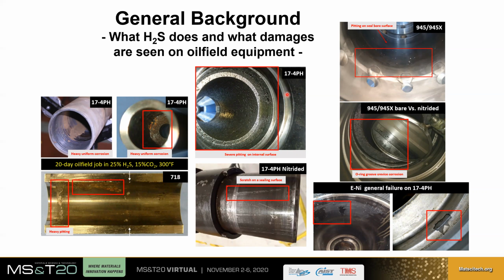For a different job, you can see here essentially heavy pitting on the internal diameter of some pressure housing. On the lower picture, you see a different type of damage, which is not really H2S specific, but nonetheless is very common in equipment. What we see here is a scratch. There was a sealing surface, there is a scratch. That means this surface is not going to have the same sealing ability, and it's a damage. Because this type of damage is quite common, this is one reason why we are forced to look at tribological solutions, namely hard coatings and hard surface treatments. And this is what we'll be discussing mostly in this presentation.